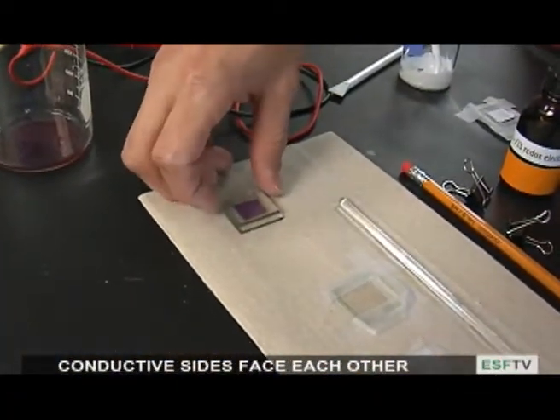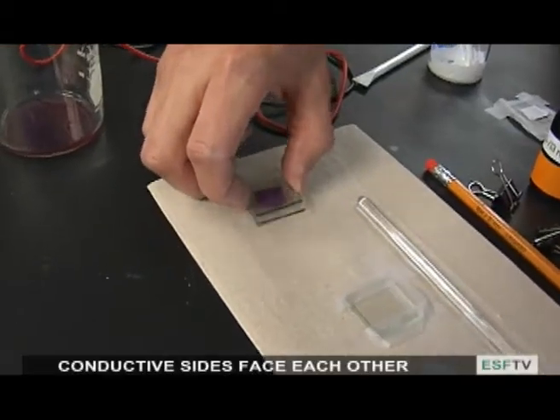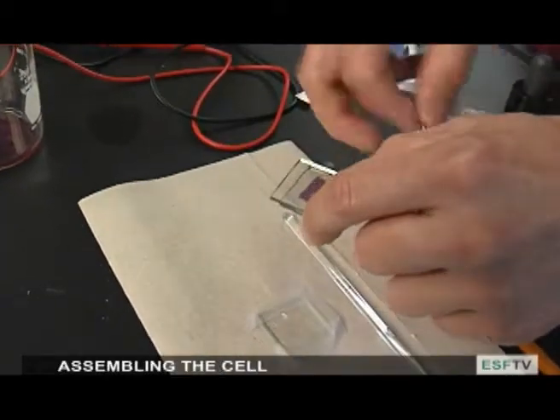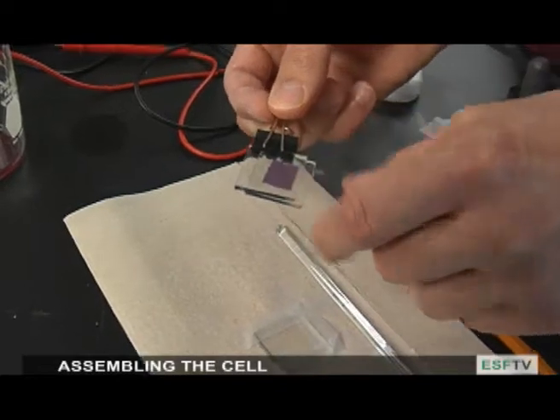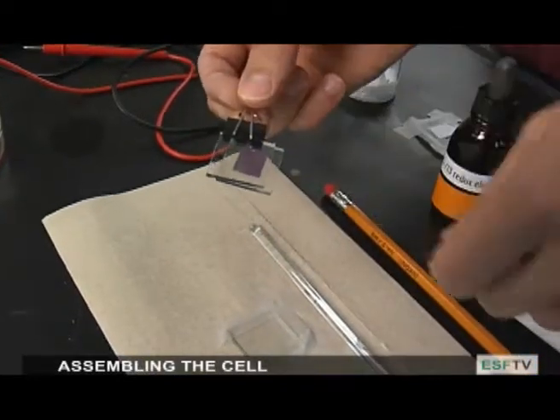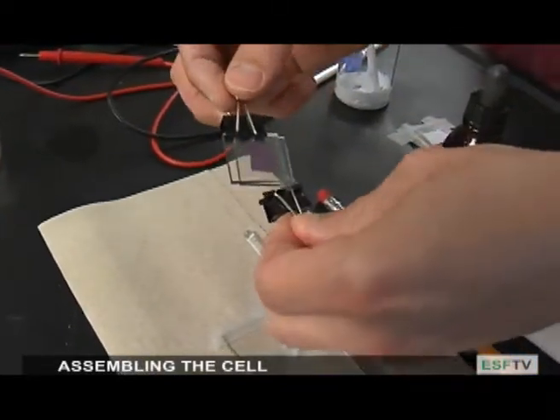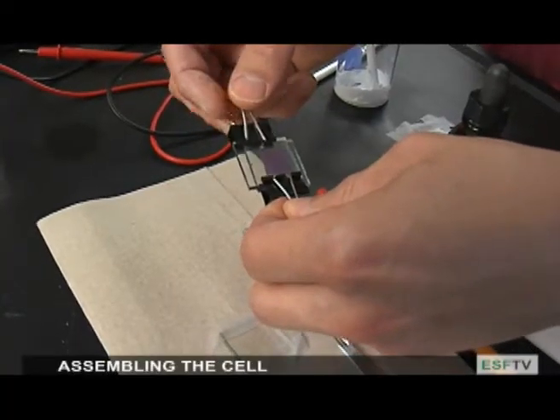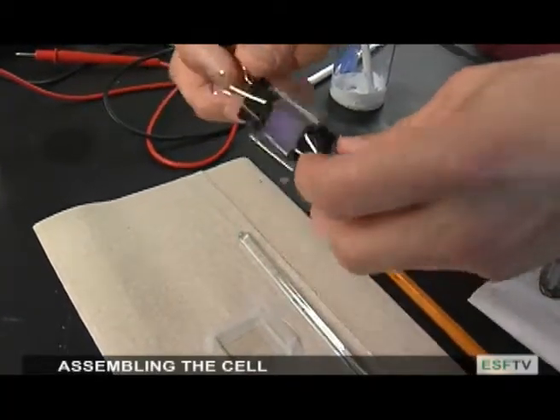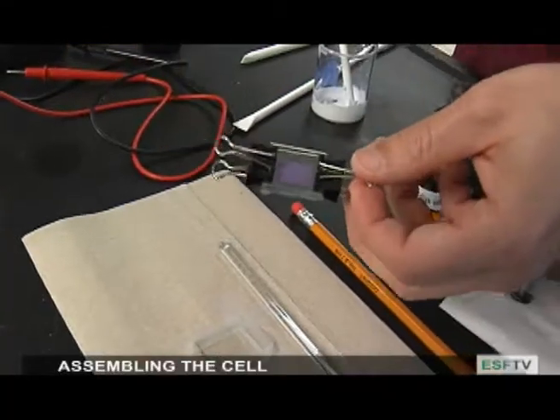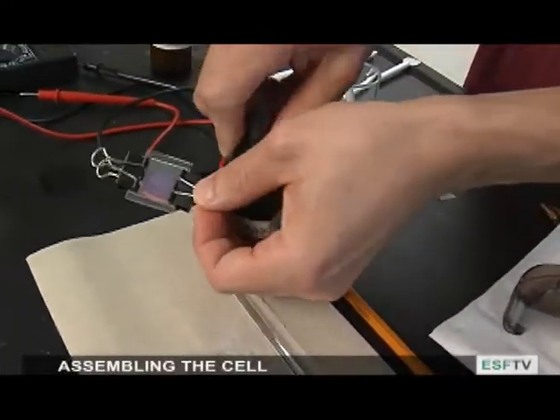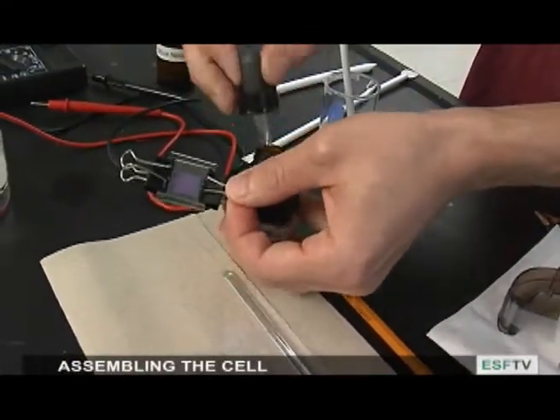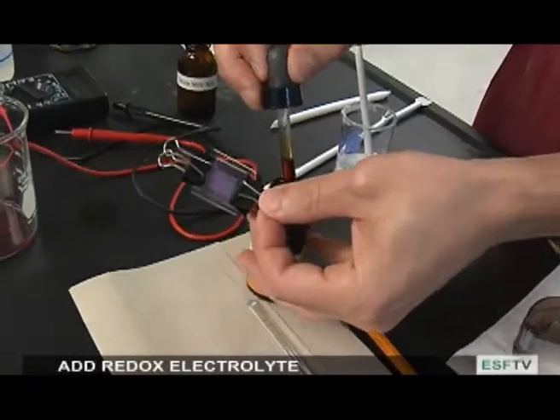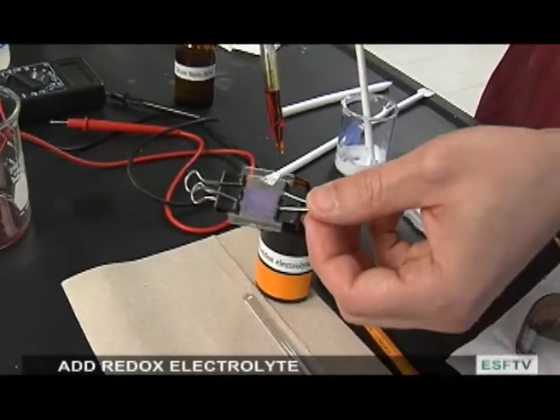If you're unsure about the conductive side, just use your multimeter. We're then going to take the cell and clamp it together using some binder clips, making sure to offset the edges so we can apply our multimeter probes. At this stage, the cell is ready to go, except that there's no conductivity. We're going to add the conductivity using a redox electrolyte made of iodine and potassium iodide.